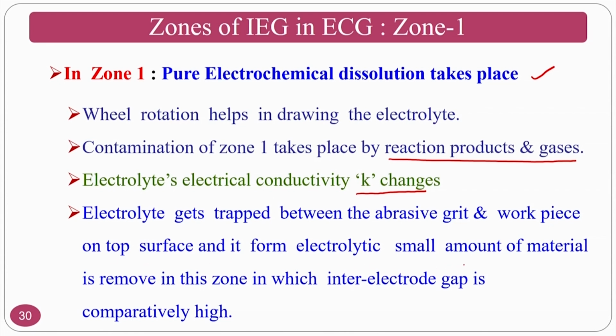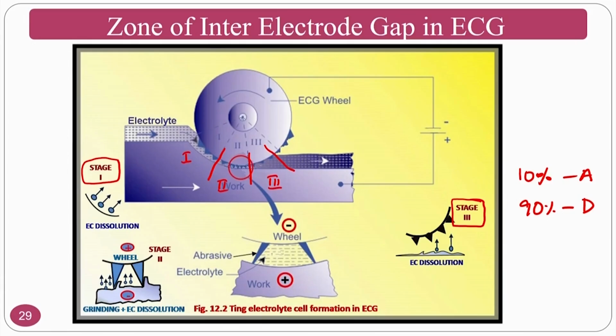From the electrolytic action, small amounts of material are removed in this zone, where the inter-electrode gap is comparatively high. That means the material removal mechanism here is completely dominated by the electrochemical dissolution process, because there is no abrasion action. If you can see here, you have a complete gap in stage 1. There is no abrasion action. The abrasives are not at all touching the workpiece. That is why the material removal mechanism is completely by electrochemical dissolution only.